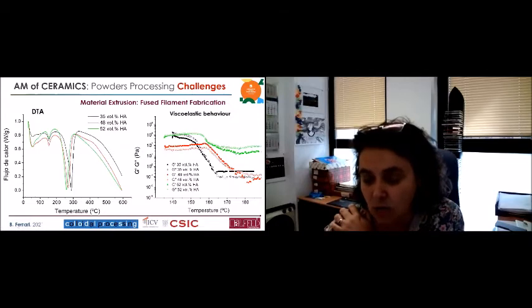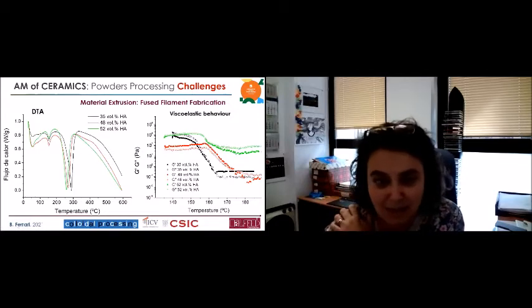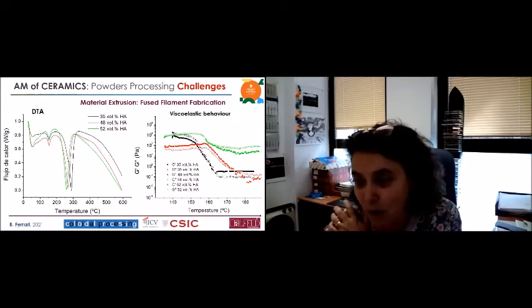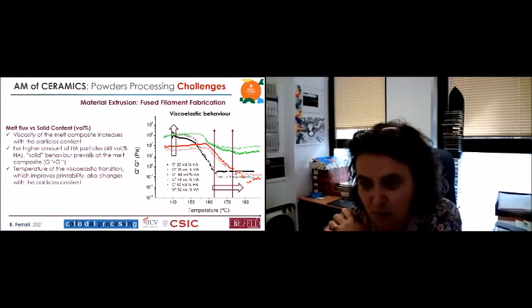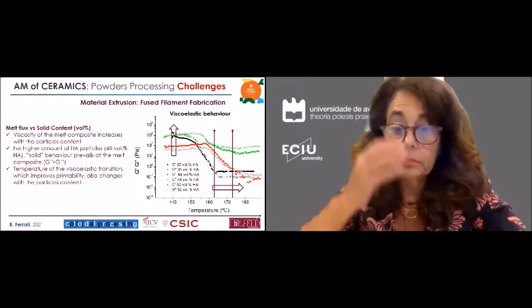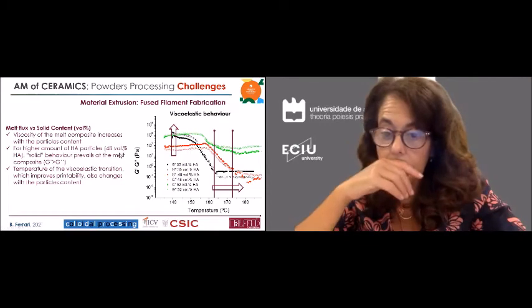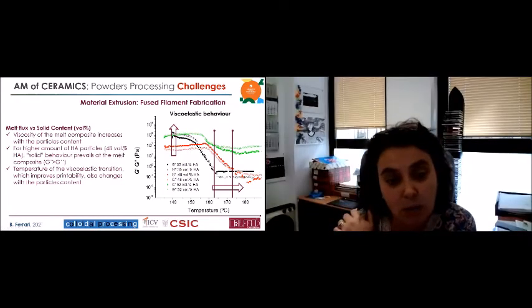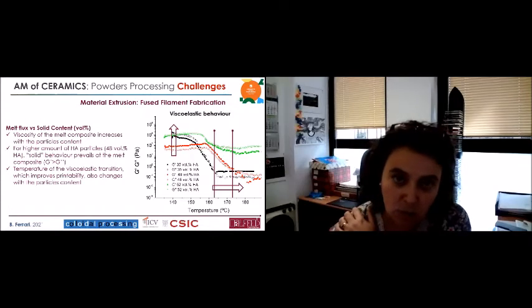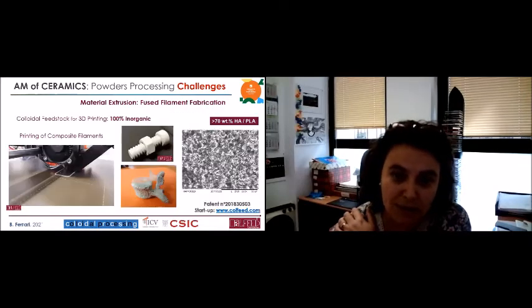You see that the rheology is not exactly the same as the gelling one. It is a stranger rheology, right? You must define how much viscosity you have there. It's huge, the viscosity here. And also you need to know when this filament is passing from the solid to the liquid part, and also to the solid again, right? So you need to study this rheology very well.